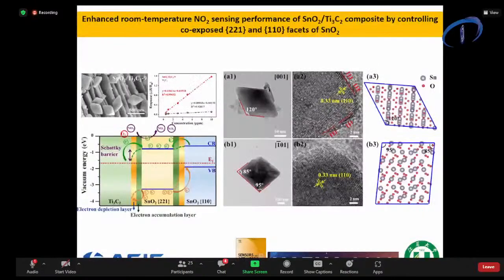And the other one is on SnO2 with the MXene material. This material is for room temperature sensing, and the composition is a tin oxide and titanium carbide composite, where we try to control the facet. You can see in the figure on the right side, the MXene material is used as a template, and polyhedral-shaped particles have been embedded, or are floating on the outside of the MXene material.